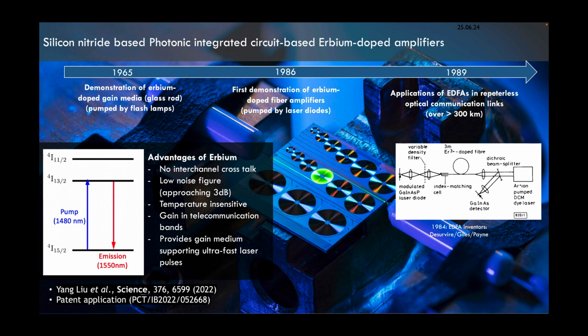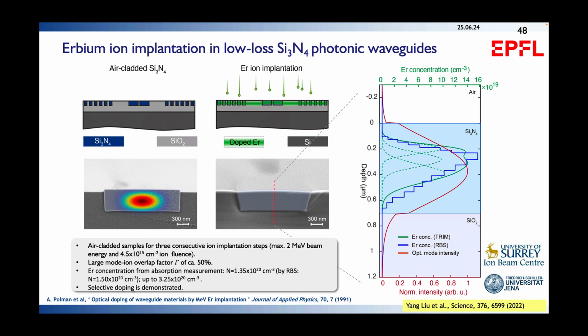It's challenging because Erbium actually gives very low gain. So the gain of Erbium, even in a high concentration limit, is typically on the level of dB per centimeter. So what you need is a host with very low optical losses. And so what we've recently demonstrated is that by using silicon nitride and using ion implantation, a very well-established manufacturing step in the semiconductor industry, we can implant Erbium ions inside the silicon nitride waveguides while retaining their very low loss, and thereby have very good optical overlap, as shown here in the Rutherford backscattering, of the silicon nitride waveguide mode, as well as the Erbium concentration profile.